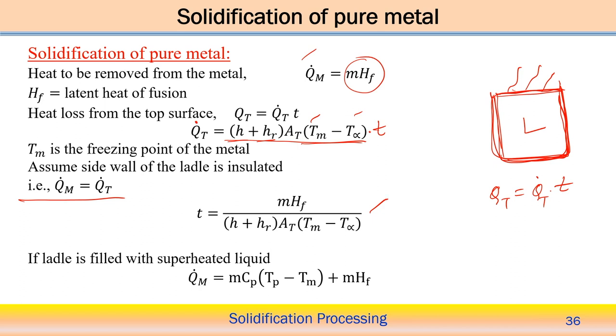Now if the ladle is filled with superheated liquid, in this case we are considering only mHf, the phase change from liquid phase to solid phase, and this phase change occurs at the melting point temperature Tm only. But with superheated liquid, you need to extract the specific heat associated with the superheat. So the superheat of the molten metal, total heat content, is m Cp (Tp minus Tm), where Tp is the peak or superheated temperature, to reach the melting point temperature.